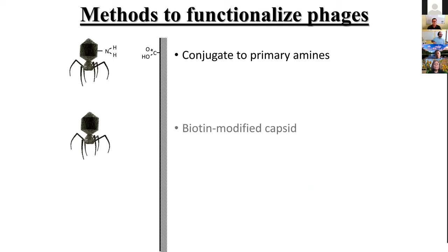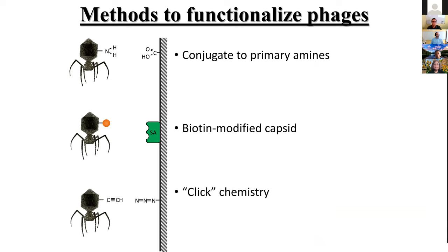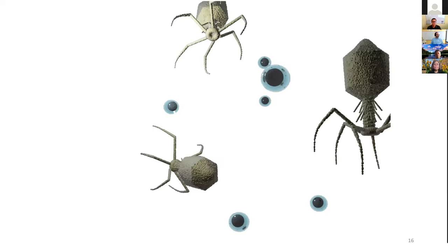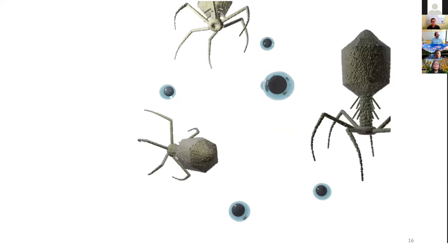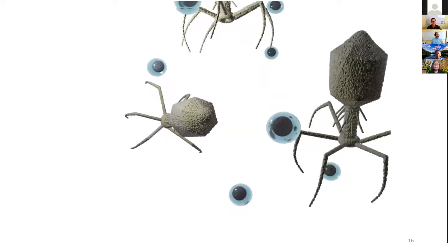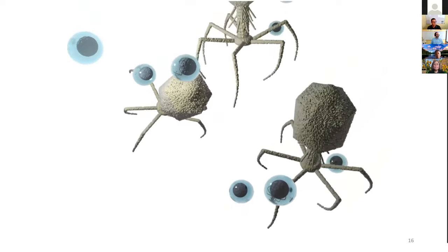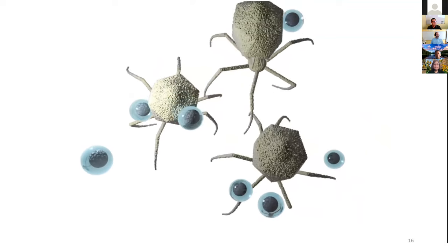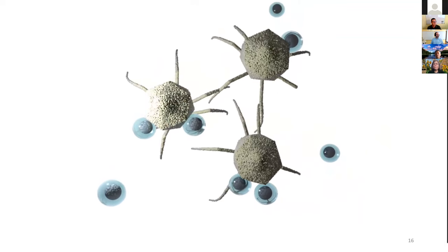We've looked at biotin modified capsids. So if we put a specific tag on, we can use enzymatic conversion to put biotin on there. And as many of you may know, biotin and streptavidin can bind fairly strongly together. The issue here is that purified streptavidin to be used in an assay where we have meters squared of nanoparticles gets pretty expensive. And that's why we decided on click chemistry. The goal, of course, is to have our phage in solution with the particles and then be able to rapidly bind on, as we can see here.